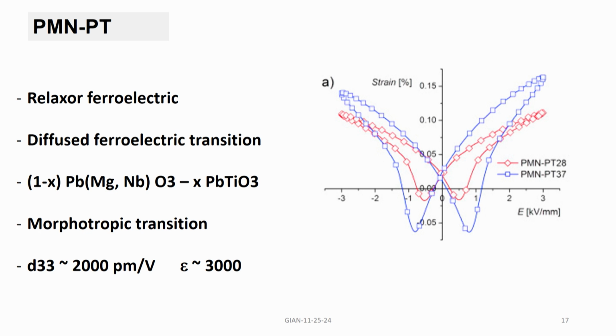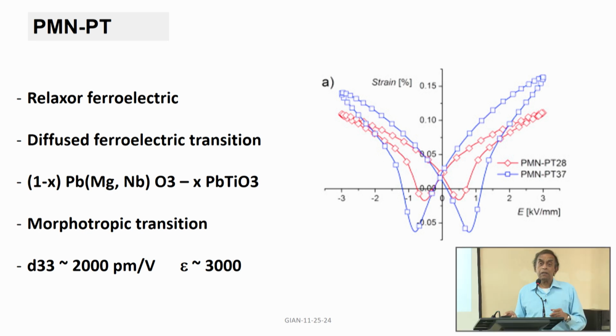PMN-PT is a relaxor ferroelectric. The difference between PZT and PMN-PT is that in the case of PMN-PT, the transition from paraelectric to ferroelectricity occurs over a wide temperature range. It's not very sharp, it's rather slow, but apart from that, it has a very good piezoelectric coefficient on the order of several thousand, and the dielectric permittivity is also quite high.